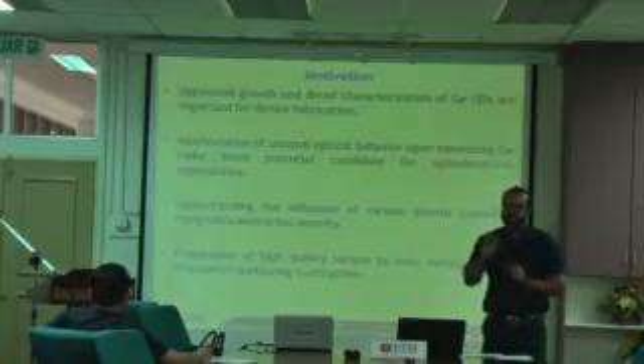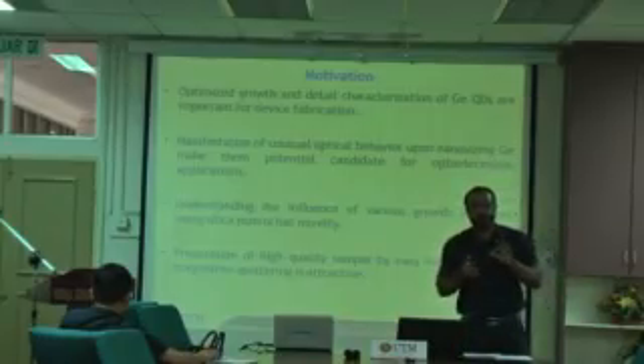Okay, so this is our motivation. The other thing is that most researchers directly deposit the germanium quantum dots on silicon. So we use silica, I mean SiO2, as an intermediate layer. It has an effect on the top layer because of the growth modes. I don't know if you have information about growth modes or not. We have three kinds of growth mode: Stranski-Krastanov, Volmer-Weber, and Frank-van der Merwe. Germanium on silicon follows the SK mode, but germanium on SiO2 follows Volmer-Weber.